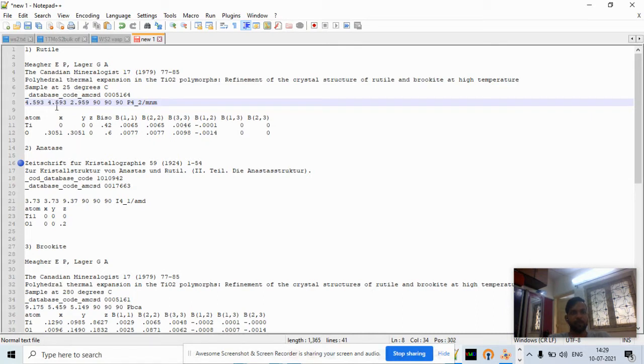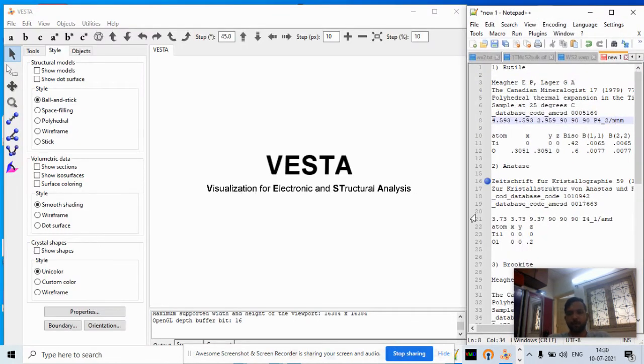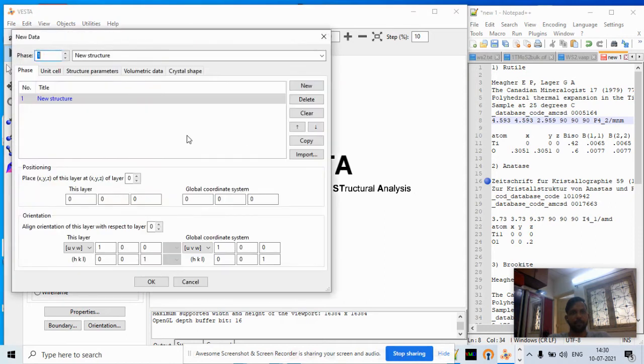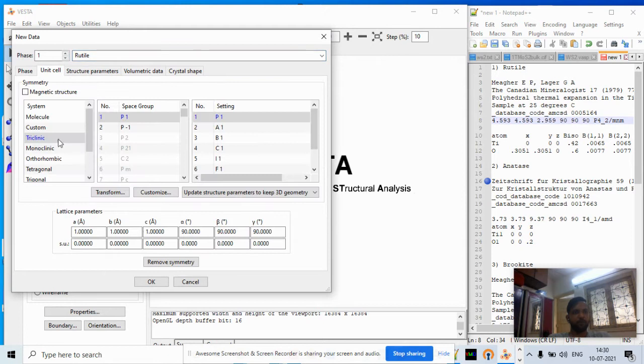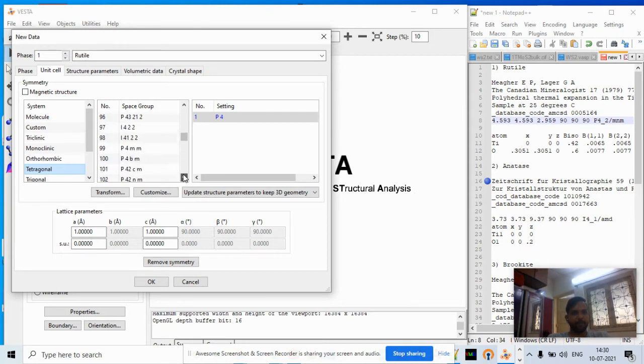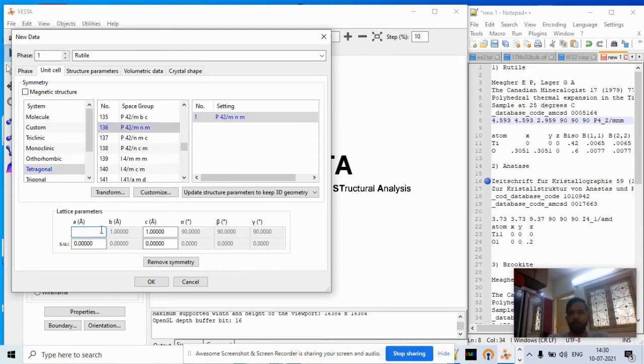Each phase has a very different crystal structure. Now let's build the structural model. We go to File > New Structure, type 'rutile', then go to Unit Cell, select tetragonal, and choose entry 136, which corresponds to space group P4₂/mnm.